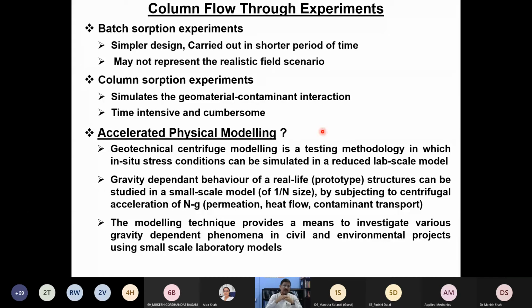It's very, very difficult. In order to avoid this particular problem, what we did is we tried to accelerate the process by using a geotechnical centrifuge. We didn't really accelerate the sorption phenomena, but we accelerated the flow rate. We are able to accelerate the seepage velocity. We assume that even under the accelerated seepage velocity, the effect of contaminant interaction time is not really reflected in the contaminant transport properties.